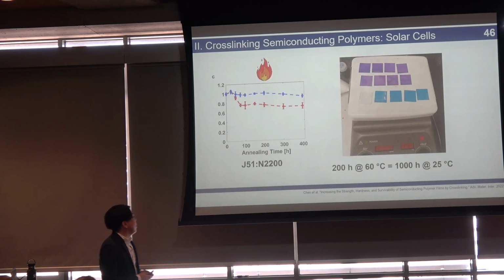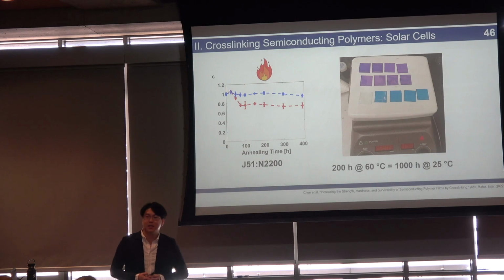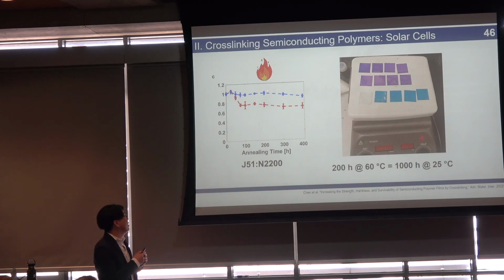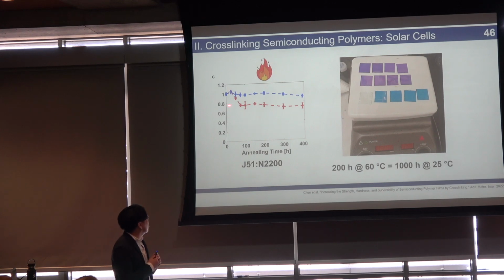We could also check the thermal aging of our material, and we see that cross-linked solar cells survive to about 200 hours at 60 degrees Celsius without any sort of degradation, whereas non-cross-linked solar cells degrade below 100 hours.